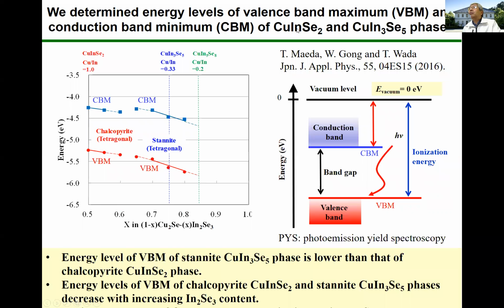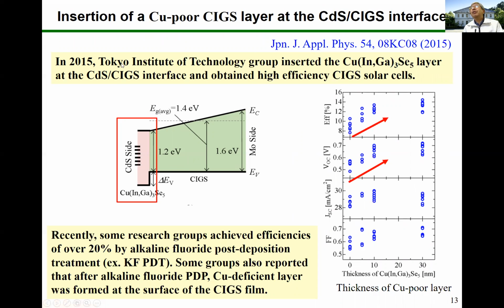We determined the energy level of the valence band maximum and conduction band minimum of chalcopyrite and stannite phase. The energy level of the valence band maximum of the stannite phase is lower than that of the chalcopyrite phase. The energy level of the valence band maximum of chalcopyrite and stannite phase decreases with increasing In2Se3 content. In 2015, the Tokyo Institute of Technology group, Professor Yamada's group, inserted a Cu-poor CuIn3Se5 (Cu(In,Ga)3Se5) CIGS layer at the CdS-CIGS interface and obtained high efficiency CIGS solar cells.